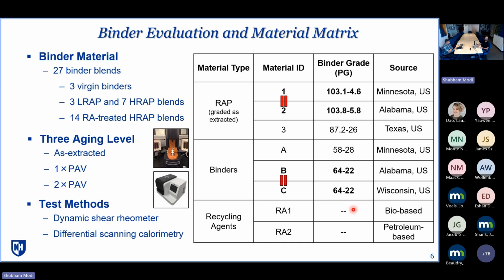So this table shows our core material matrix, which includes 3 RAP sources, 3 binder sources, and 2 recycling agents. These materials were meticulously procured in a way that two RAPs share similar extracted binder performance grades, so that we can make our conclusions based on the performance compatibility perspective, rather than PG playing a role in the research as well. The same goes for the binder selection: 2 binders were sharing the similar performance grade. And for recycling agents, one was bio-based and the other was petroleum-based.